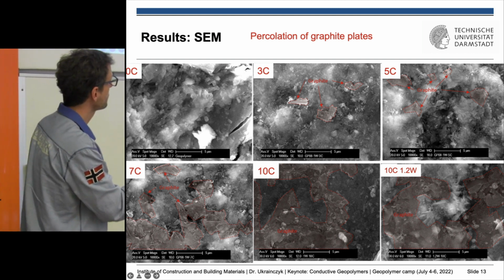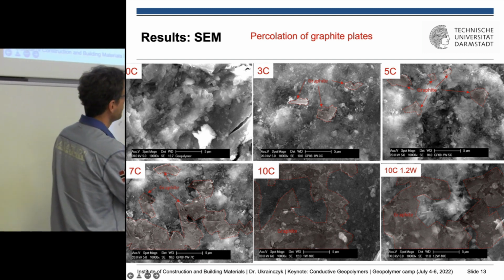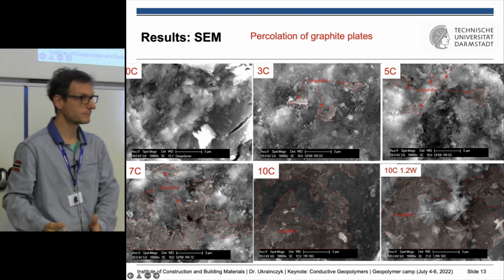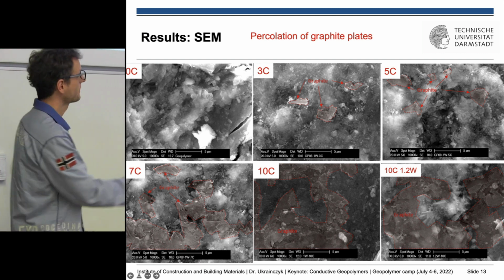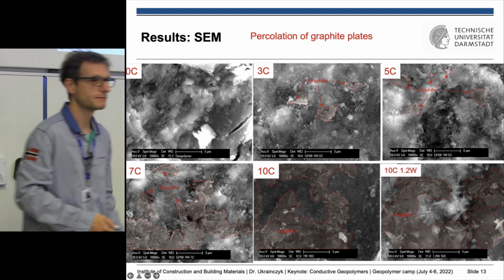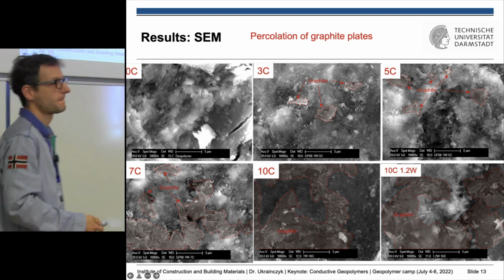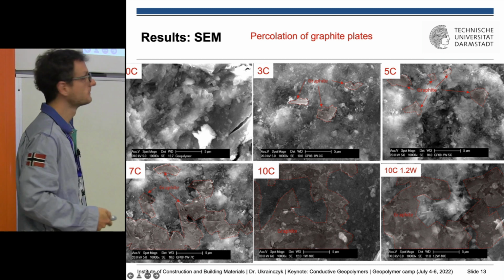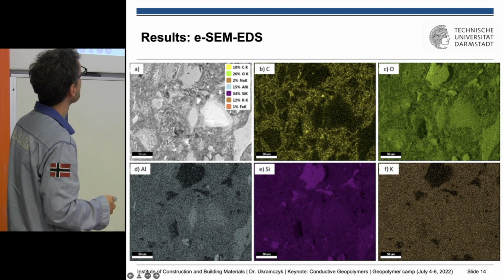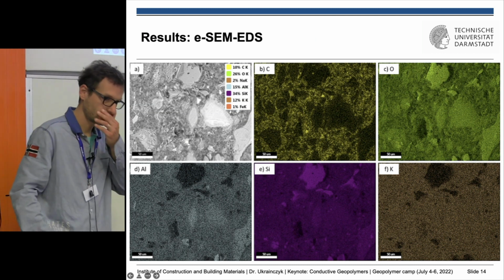So this is for 10%, but as I told you, when we add water, we are actually increasing the volume fraction in the solid part. And this is how we also explain the better conductivity when we add water. Now we also did some